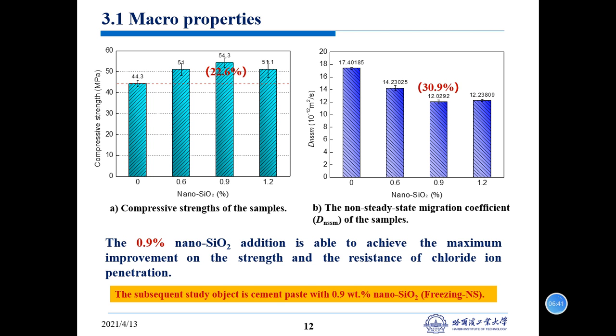And similarly, we also see the migration coefficient was decreased by 30.9% at the content of 0.9% like this. So we can see the 0.9% nanosilica addition is able to achieve the maximum improvement on the strength and the resistance of chloride ion penetration. Based on this result, we choose the cement paste with 0.9% nanosilica as the subsequent study object, and we will call it the freezing NS.